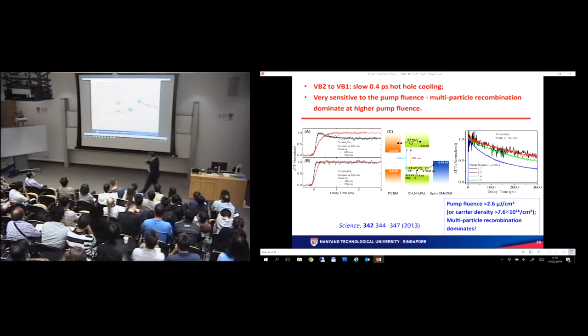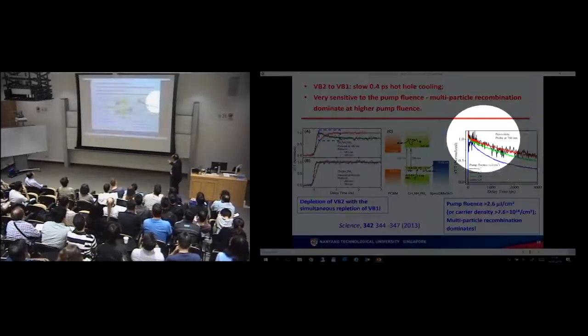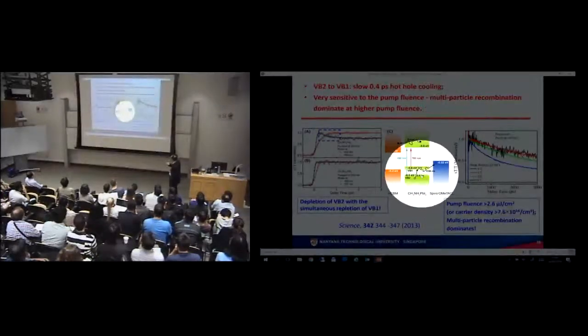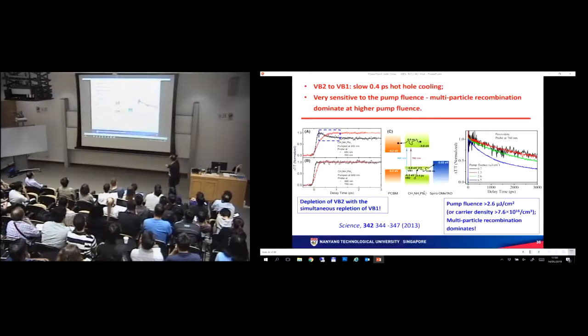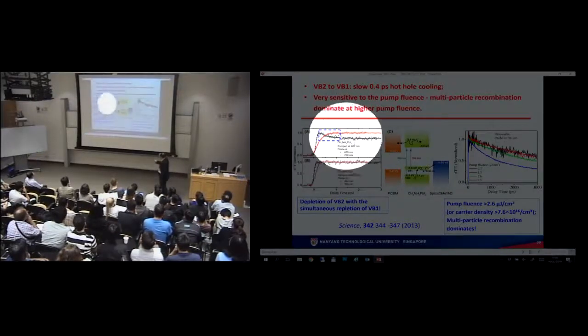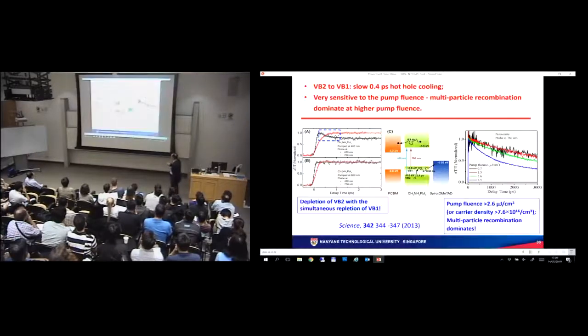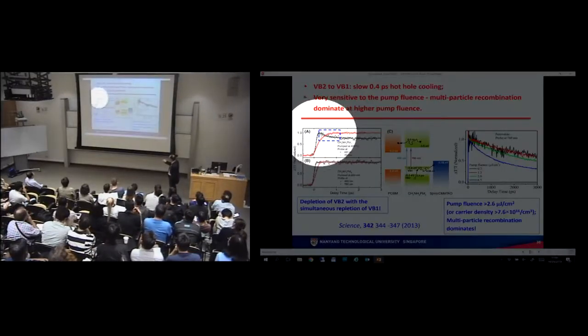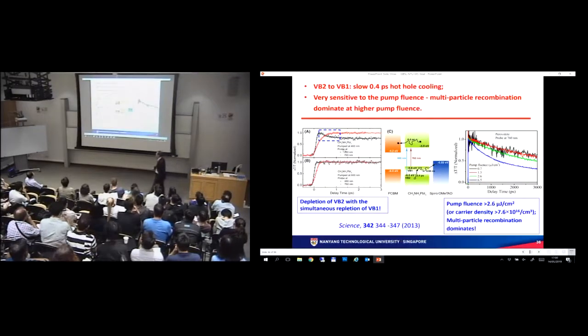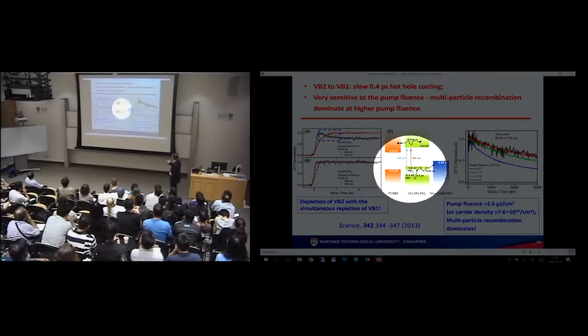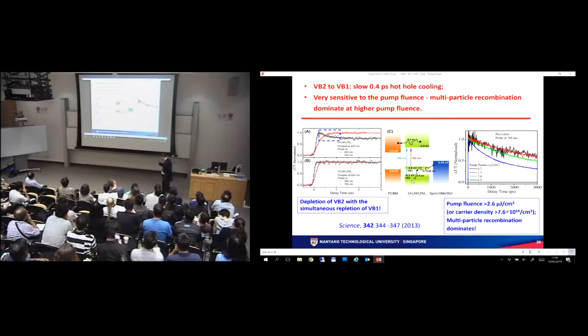Now, this is the smaller point, where we found that there's a very interesting slow hot carrier cooling process occurring in these valence bands. We see that from the interacting dynamics, from the depletion of one level, which is shown by the decay of the signal, the black signal, and the rise of another signal when we are monitoring a higher valence band level. So you can imagine this level is losing its carriers as the hole is behaving like a bubble and floating up to the next level. So that level is emptying out while the upper level is slowly filling up with more holes.